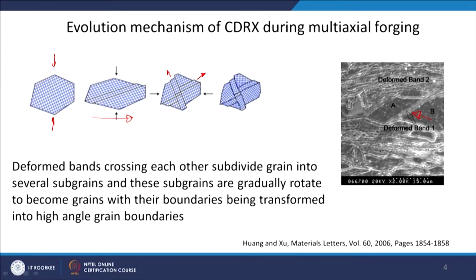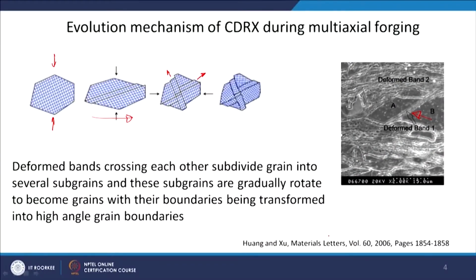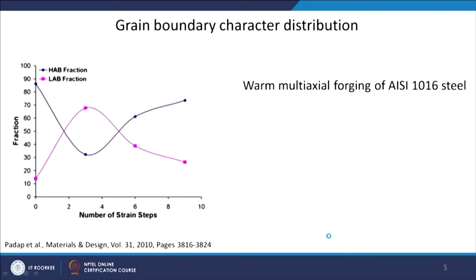And so, you will divide the grain into subgrains, and slowly the CDRX process will be through subdivision into subgrains, and then the subgrain rotation will create a high angle grain boundary. So, this gradual change from low angle to high angle grain boundary takes place by subdivision plus subgrain rotation. That is what was proposed in this particular work, and that is how you get grains with high angle grain boundaries. Now, what will be the effect on grain boundary character distribution?